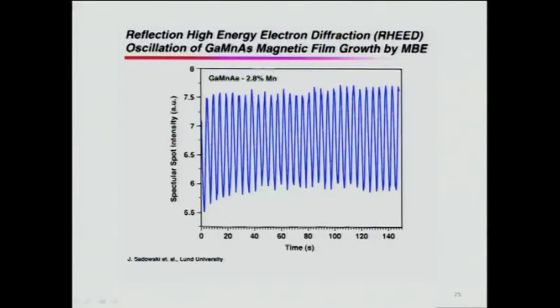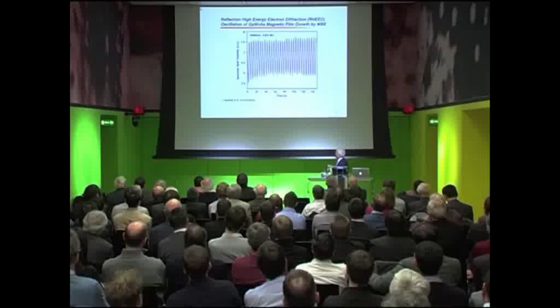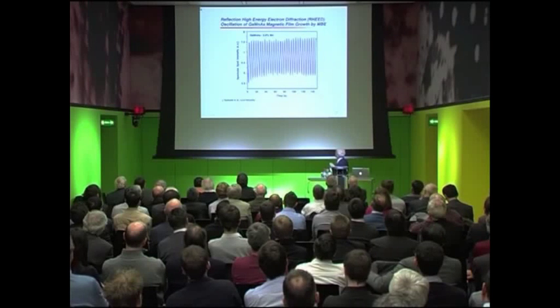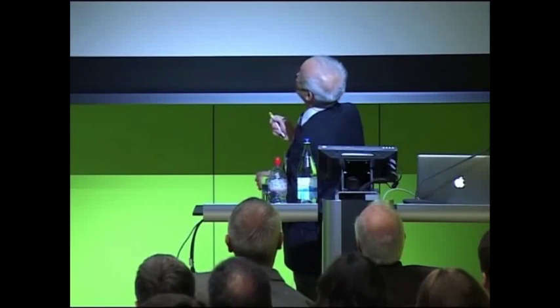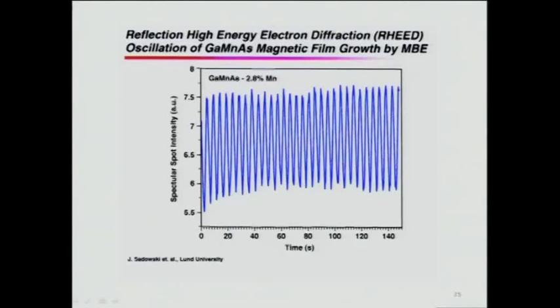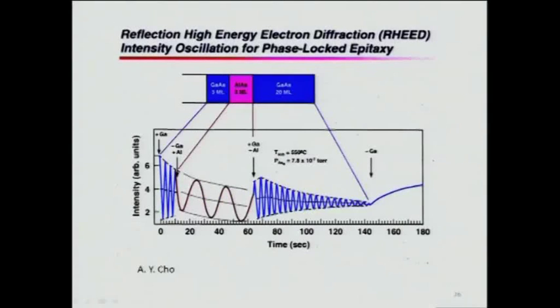Notice here, a beautiful intensity oscillation reported by Sadowski at Lund University. This shows the specularly reflected intensity, that spot, as a function of time in seconds. Notice here, beautifully, layer by layer growth by MBE technology. In this case, it is the oscillation of a gallium manganese arsenide magnetic film grown at Lund University.